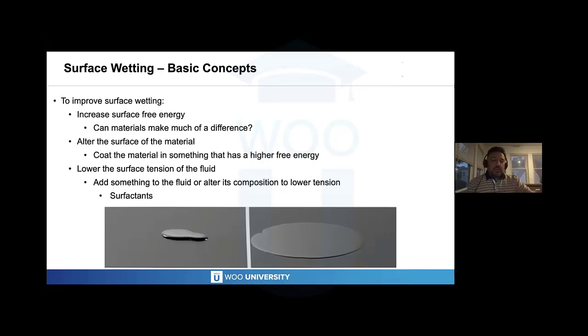And then we can also lower the surface tension of the fluid by adding things, lubricants or surfactants will create that. So the little picture on the bottom I thought was great. You have this little water blister, if you will, on the left. And by simply adding one drop of a surfactant, that immediately spreads out to a larger surface on that surface. And that's because surfactants lower the surface tension of the liquid that they're added to. So surfactants are a good thing, whether we put them in our eye in the form of lubricant drops, or if our lenses are coated with them as we apply them to the eye. They are also things that help with surface wetting.